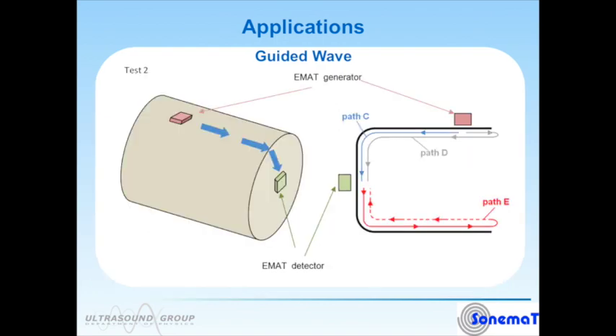One of the really interesting properties about EMATs generating these SH guided waves is that they propagate around corners with very little loss. Not just curved surfaces, but very sharp corners. In this experiment, you can see this is a stainless steel container. One EMAT is positioned on the side of the container, another EMAT is positioned on the base of the container in this case.